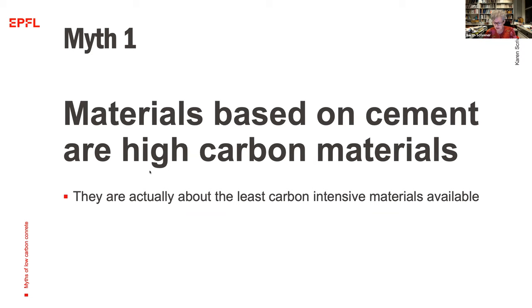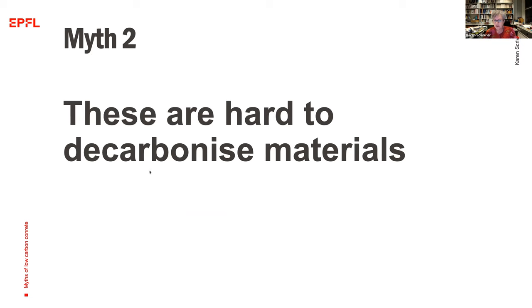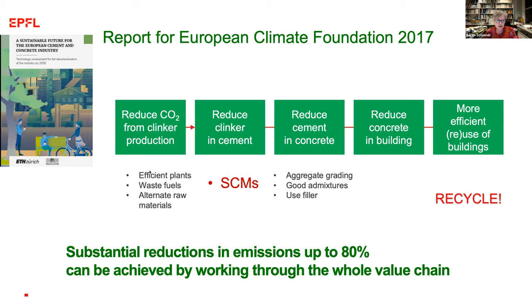So the second myth is to say that, you know, these are hard to decarbonize materials. There's nothing we can do. Now, that couldn't be further from the truth. So in 2017, we wrote this report with Guillaume Albert and Aurélie Favier, and we showed that if you really work through the value chain, that's to say you start with very efficient production of clinker, you use alternative fuels, then you minimize the clinker content in the cement by using supplementary cementitious materials.